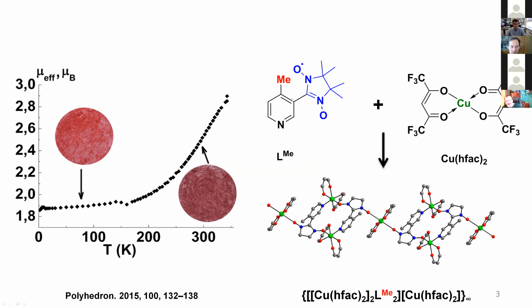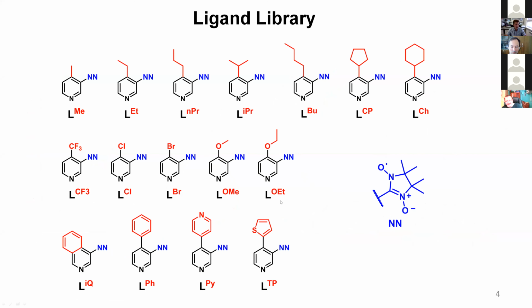Later, we decided to modify that nitroxide by varying the substituent at the fourth position of the pyridine cycle. Introducing a methyl group to this position showed the promise of our assumption, and the first polymeric chain complex with copper hexafluoroacetylacetonate, which undergoes a reversible spin transition at approximately room temperature with a color change, was obtained. After that, we synthesized a library of ligands with different types and volumes of substituents at the fourth position of the pyridine cycle. In my presentation, I will talk only about nitronyl nitroxides.